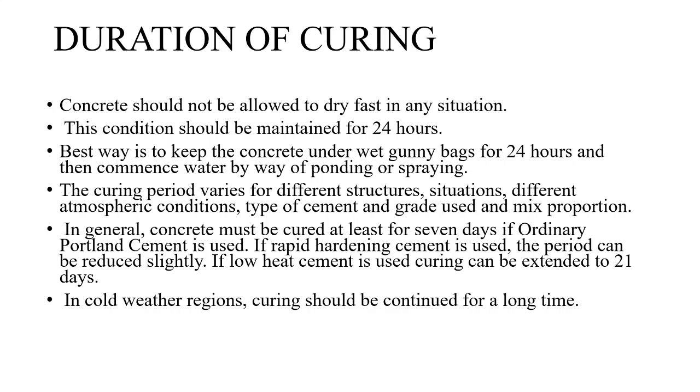Now the point is duration of curing. For how many days should one cure the concrete? Concrete should not be allowed to dry fast in any situation. This condition should be maintained for 24 hours. The best way is to keep the concrete under wet gunny bags for 24 hours and then commence water curing by way of ponding and spraying.